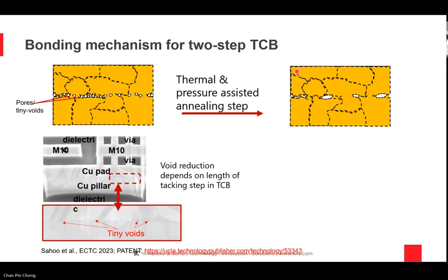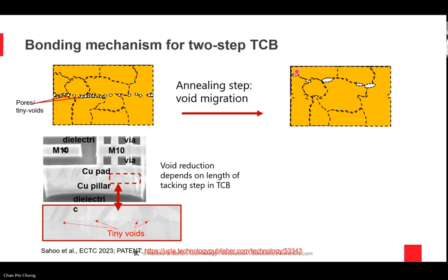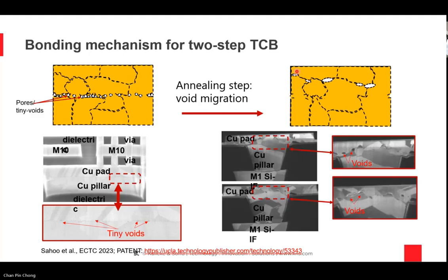So you could actually get to the point where these voids are very, very far away from the interface, and there is no fundamental issue anymore. By the way, if you do this with hybrid bonding, you will see very much the same effect, because at the microscopic level, these two are the same. The big difference between hybrid and TCB lies in the fact that we are only controlling one thing in TCB, while we have to do two things at the same time in hybrid bonding.